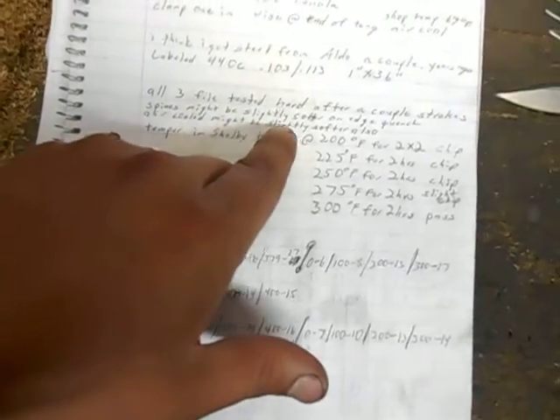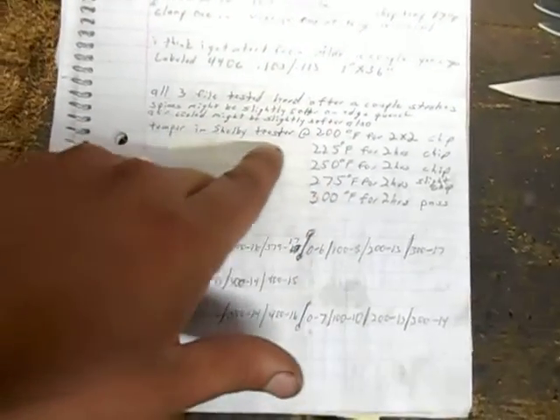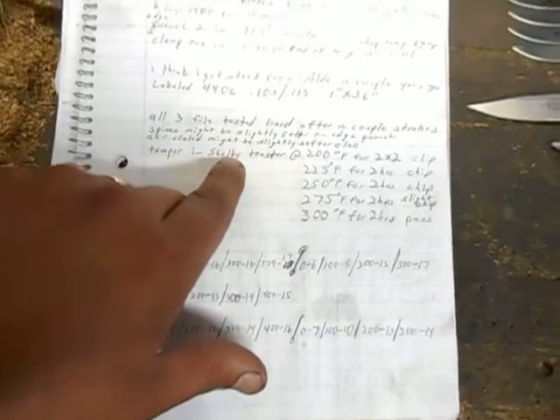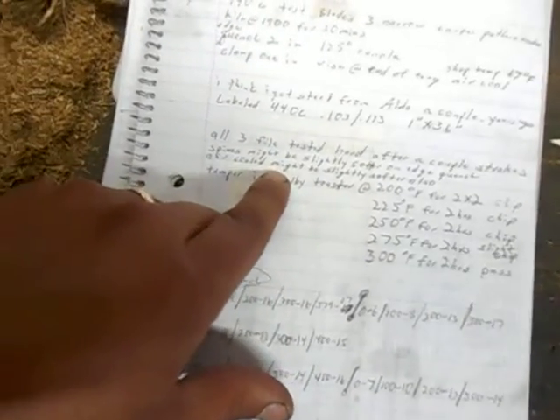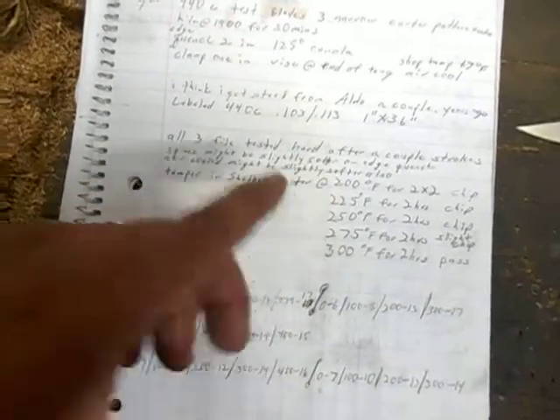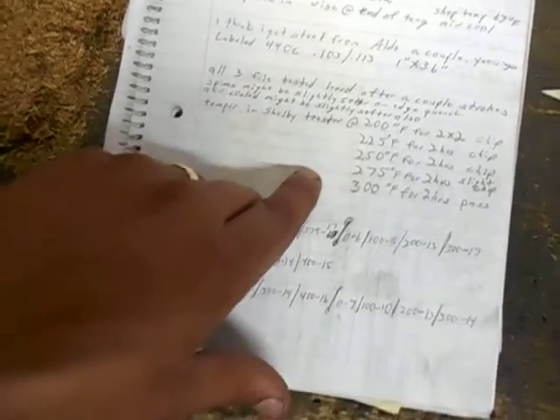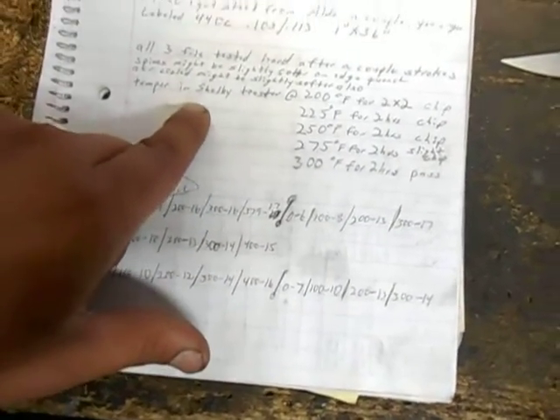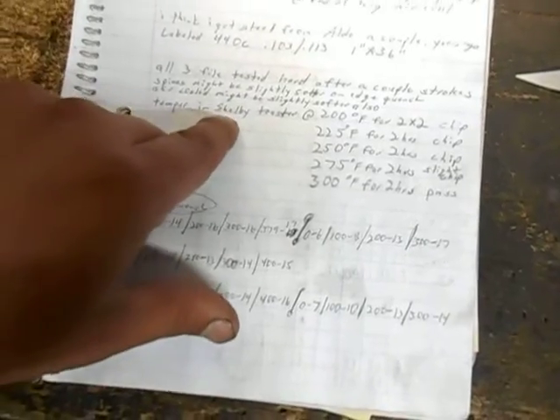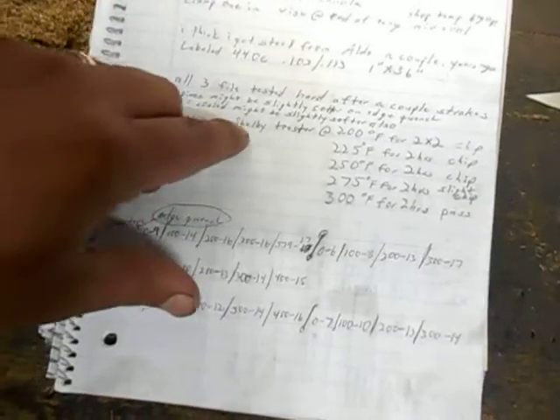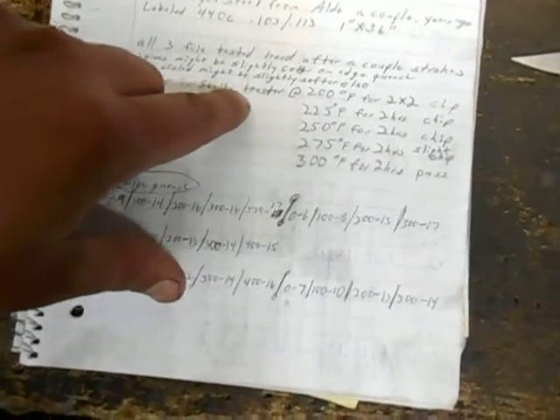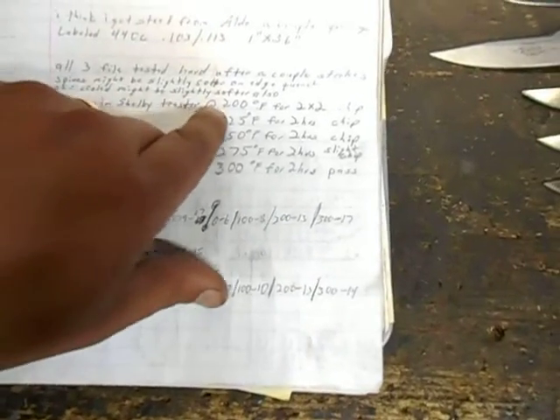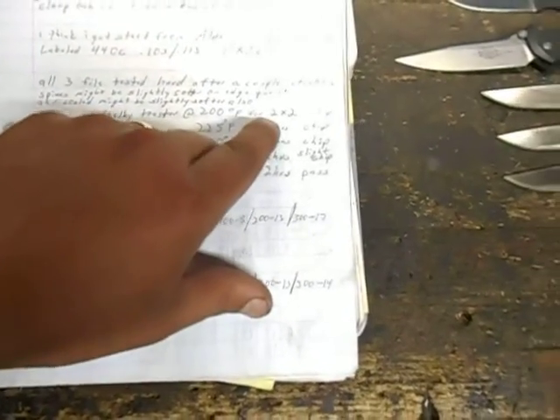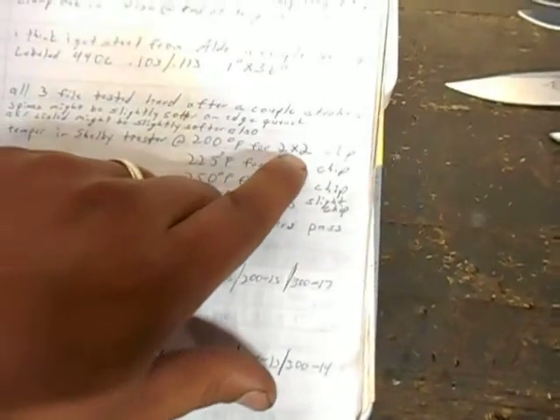The air quenched one might have been slightly softer. The spines on the edge quenched ones, it says, may have been slightly softer, but I don't think I would have sworn to that. So then I tempered them, and I've got two toasters that I use. This one's the Shelby toaster. That's because that's where I got it. Shelby's my daughter. So I stuck them in there at 200 degrees for 2 hours and did it twice, and